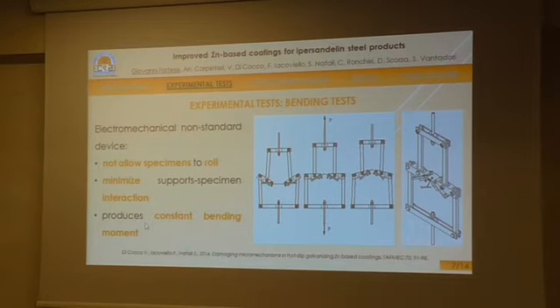For each series of specimens, experimental bending tests were performed by employing an electromechanical non-standard device shown in the figure on the right-hand side. Such a device doesn't allow specimens to roll, minimizing the interaction with supports, and ensures a constant bending moment in all the sections of specimens.